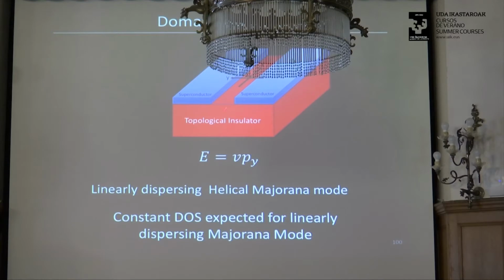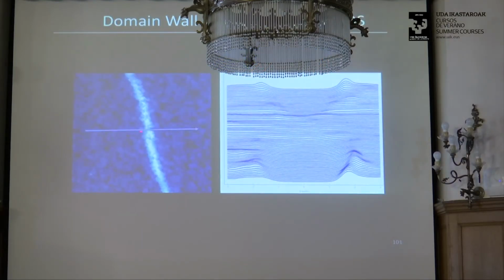So if that's the case, then what you would expect right at the boundary is this linearly dispersing state. And if you ask yourself, in one dimension, what's the density of states of something that disperses linearly? It's flat. Okay? And so in fact, that's what we believe we're seeing. We're seeing a linearly dispersing mode that goes right along this domain wall.